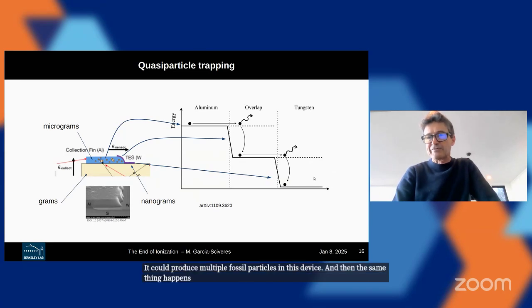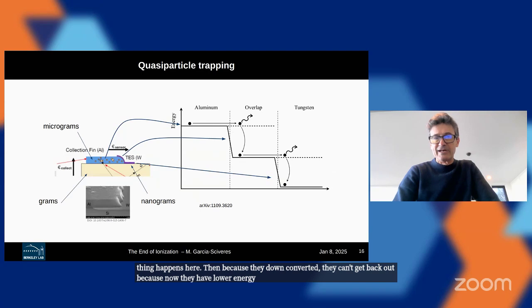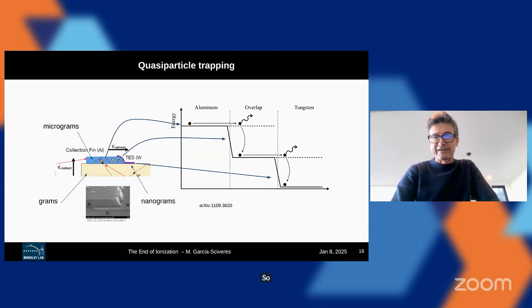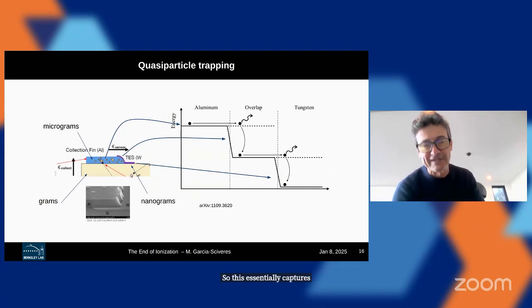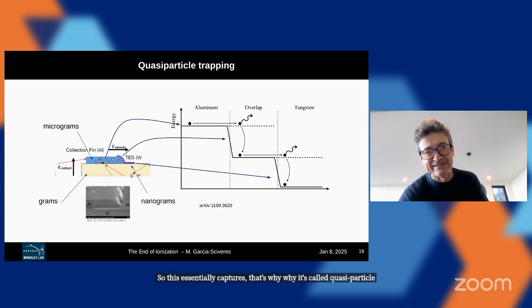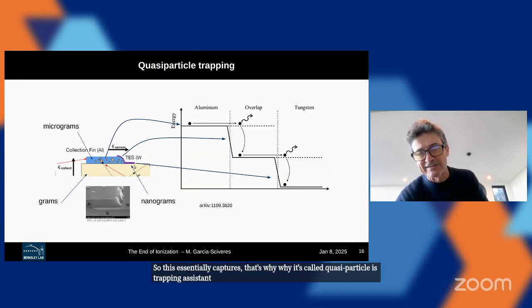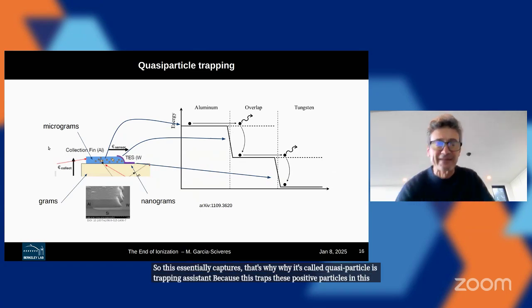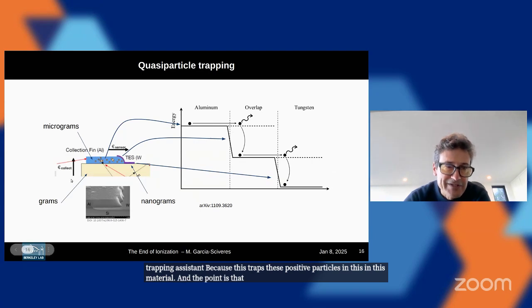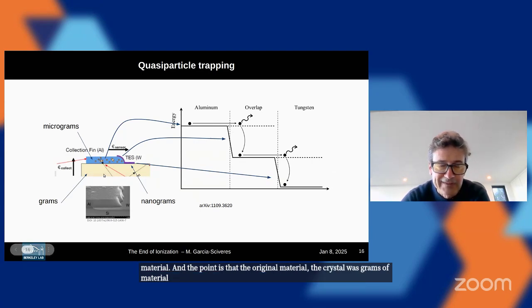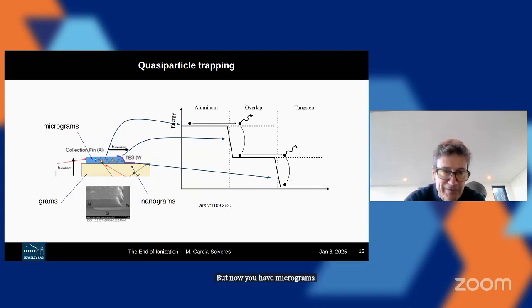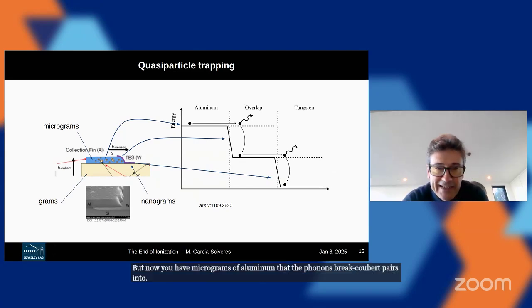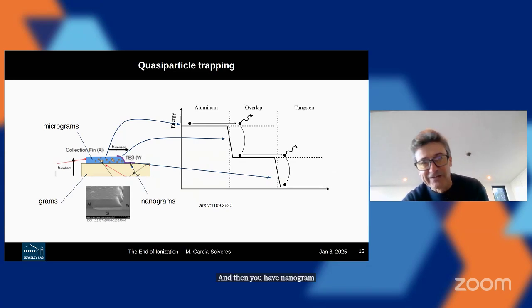Then because they down converted, they can't get back out because now they have lower energy than this energy. So this essentially captures. That's why it's called quasi-particle trapping assisted, because this traps these quasi-particles in this material. And the point is that the original material, the crystal, was grams of material. You have a few phonons in grams of material, but now you have micrograms of aluminum that the phonons break Cooper pairs into. And then you have nanograms of material that you're going to heat up.